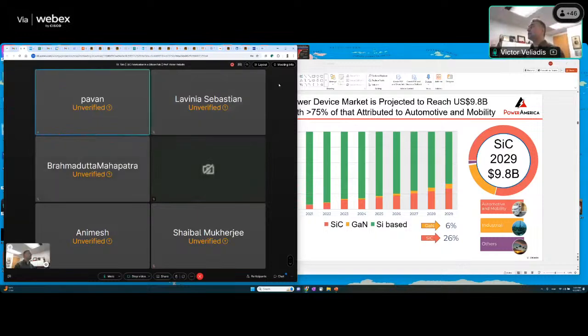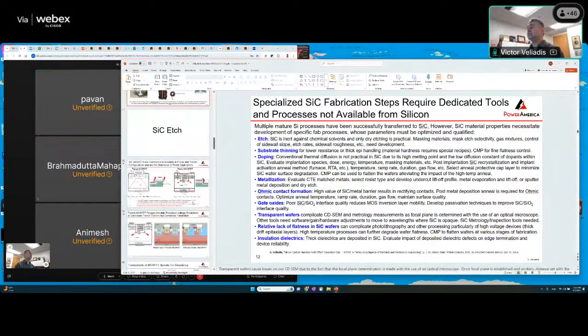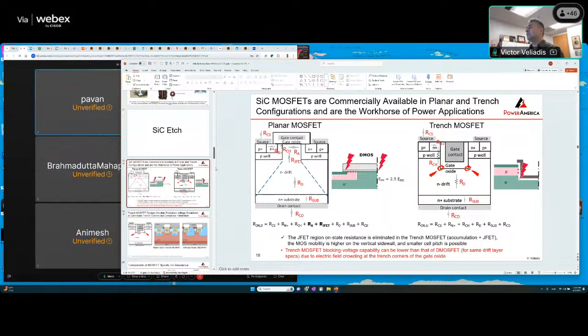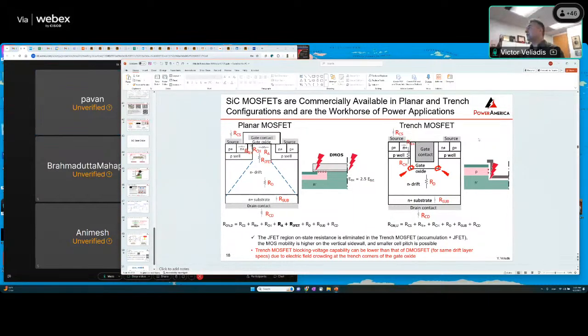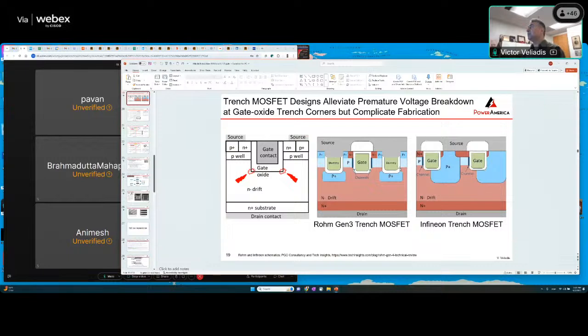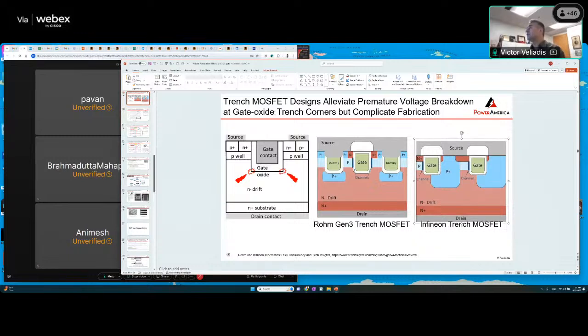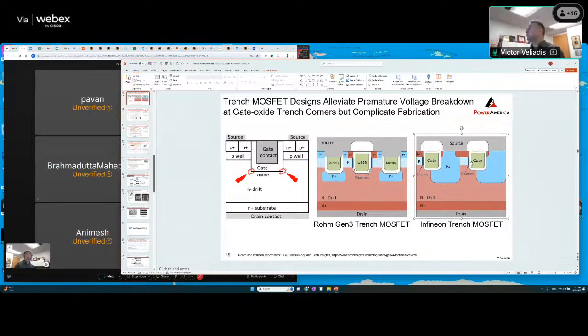Yes, if you have, and let me show the right slide. If you have a trench MOSFET, right, you have this vertical conduction, higher mobility, you have smaller area device. These are good things, but because you have this buildup of electric field in the corner that you need to take care of, then you got to come up with devices that basically either have this dummy type of edges which take space on the wafer, or in the case of Infineon, you're losing conduction over half of the gate. Instead of having conduction here, as well as right here on both sides of the gate, you only have conduction on one side.